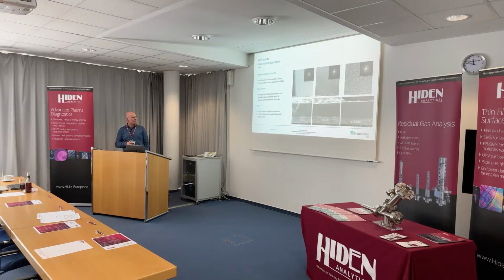And the differences, you can see here in the cross sections. In the beginning, we have TAC with really rough coatings, and we have defect structures in the TAC coatings. In this case, they are 5 micrometers thick. And if you do some break, then you see this structure. And if you go to TACB, we have the same hardness, meaning the same sp3 ratio. And here we have a very smooth film without any defects anymore.